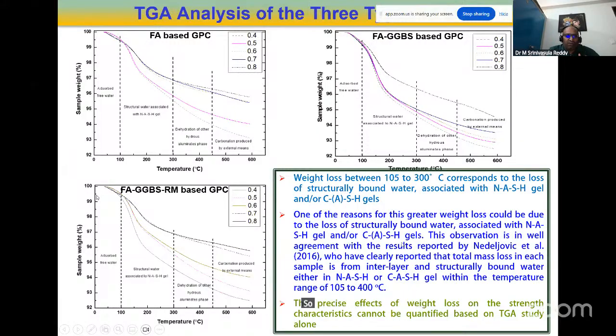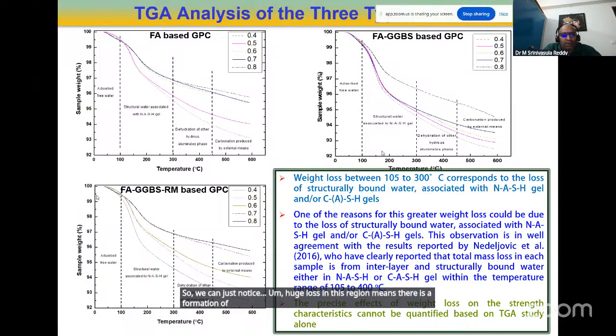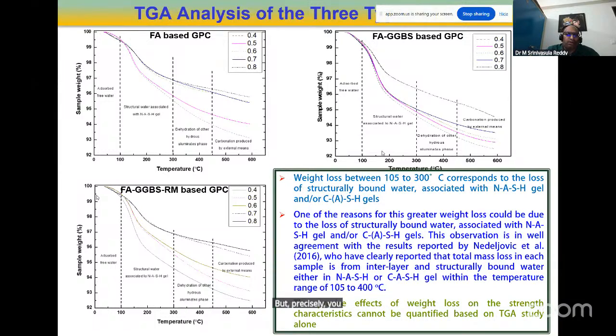So we can just notice a huge loss in this region means there is a formation of N-A-S-H, huge loss of water from the N-A-S-H gel formation. Less water loss means less N-A-S-H formation. More water loss means more N-A-S-H formation is there. But we cannot directly correlate with TGA. We specifically cannot say that because of this alone, because of more water loss, this is having more strength and this is having less strength. But precisely we cannot tell. But approximately we can say, okay, because of this reason we are noticing more loss of structurally bound water.